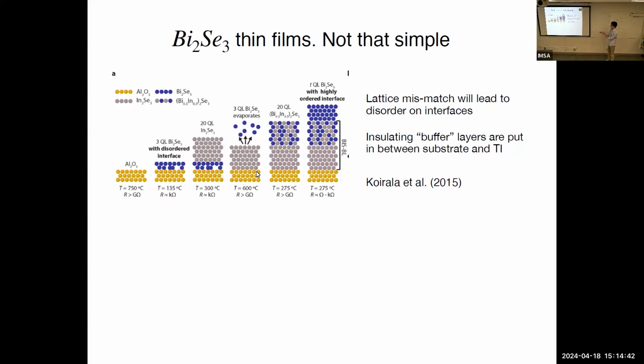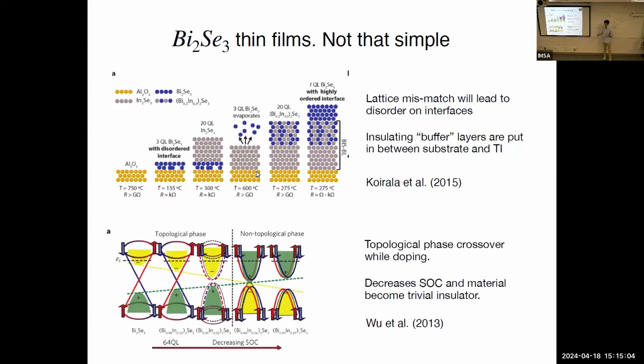And in this case, initially, a few layers of indium selenide were grown, and indium selenide is just a trivial insulator. And then the next thing was to grow a few layers of bismuth indium selenide, which could be both a topological insulator and a trivial insulator. I think Jed Pixley mentioned this transition in his talk a few days earlier. But in this case, it's all in the insulating case, and only then can you grow high quality bismuth selenide, because now there's a good lattice matching, and you can actually have a clean bismuth selenide, and all of this is just insulating. So all of this was just done to get a good clean sample of bismuth selenide.